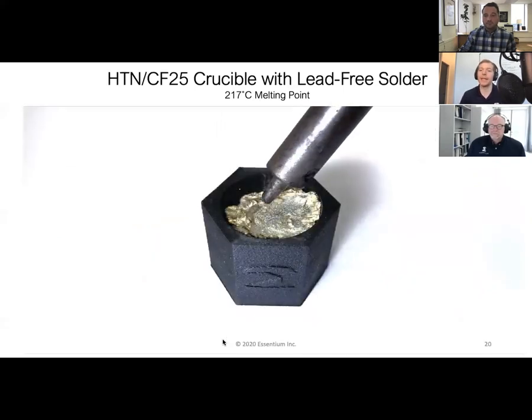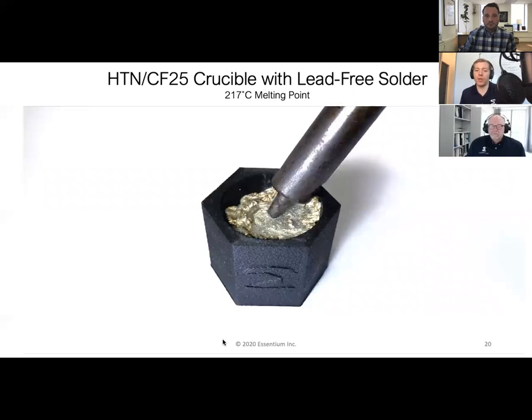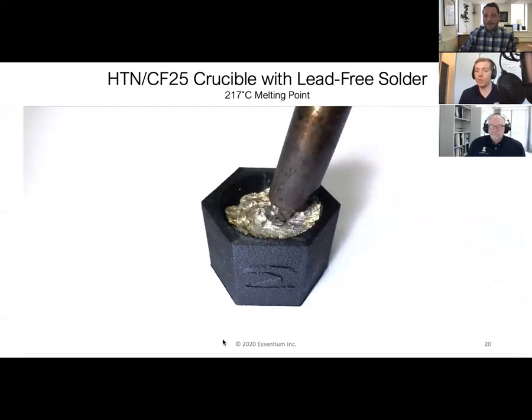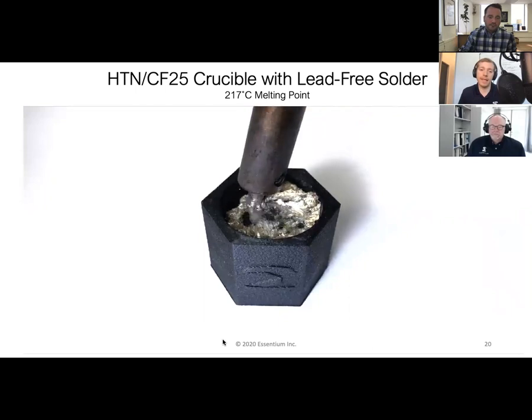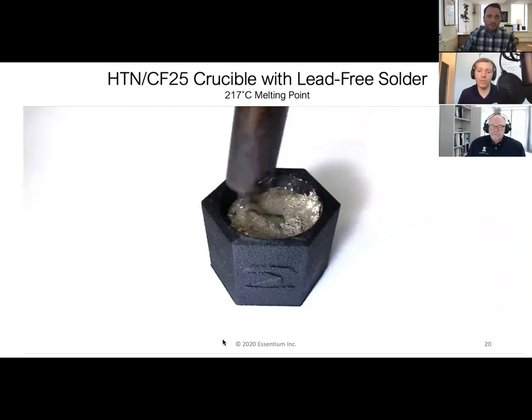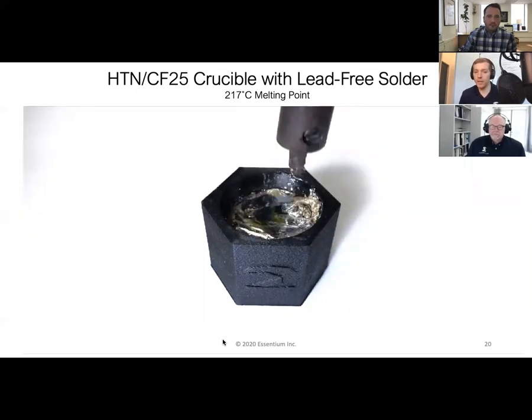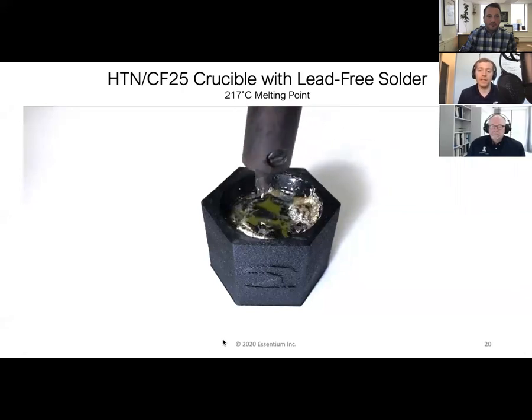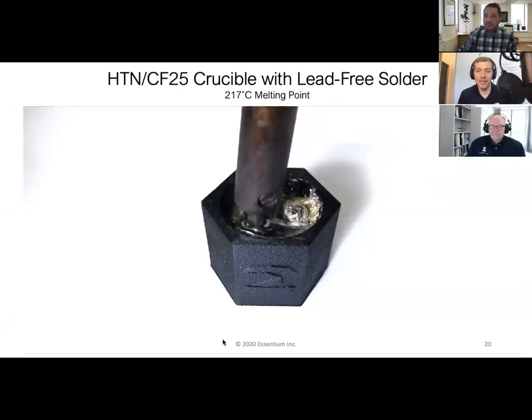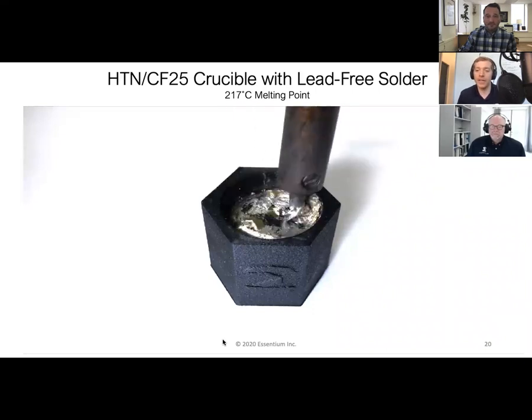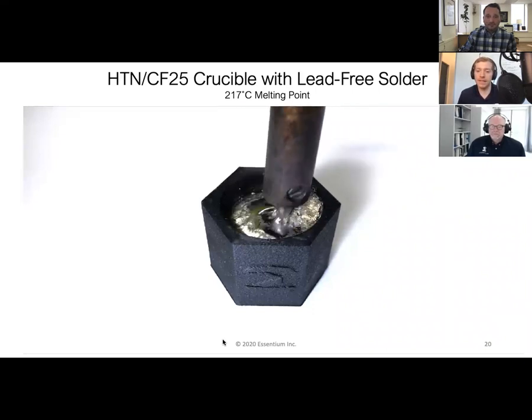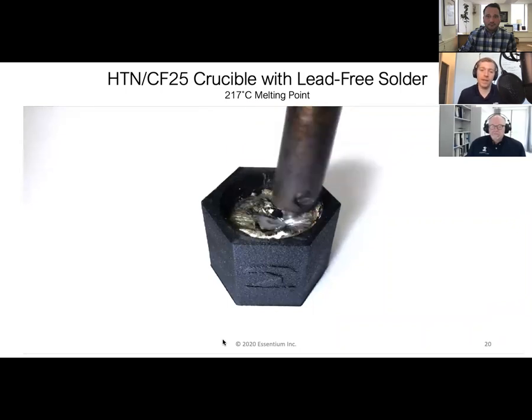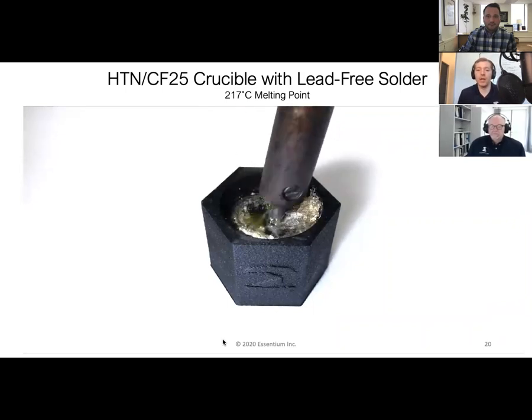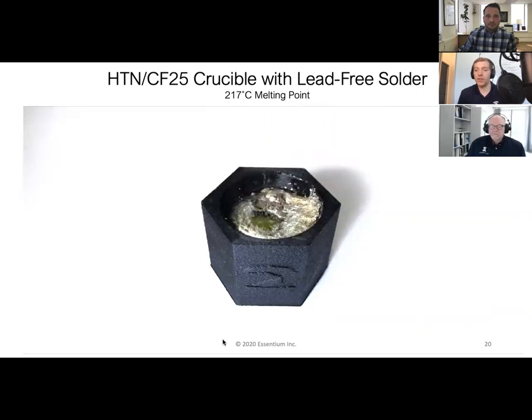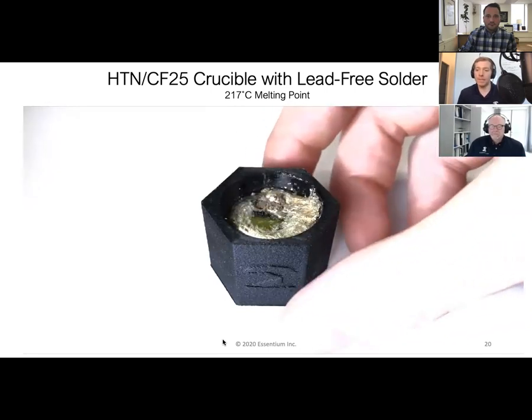Another thing that I want to highlight as an additional functional property that we'd like to consider is temperature performance. This is that same material, the HTN with 25% carbon fiber. And this is a video that we made. It's pretty crazy, but this is lead-free solder, and we created a crucible and melted the solder inside of this printed part. This was just a demonstration to show that if I'm working with soldering fixtures or things that are going to go through an SMT oven, materials like this can survive those temperatures.